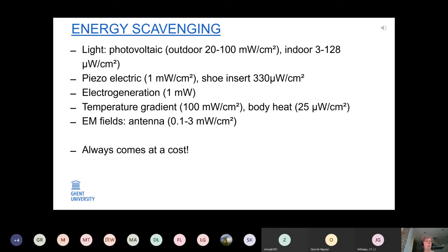But it is important to remember that energy scavenging always comes at a cost. For scavenging light, for instance, you have a dark textile, because it's absorbing the light, that's exactly what it wants to do, which may be inconvenient for textiles. With piezoelectric, you can feel that the resistance of using the textile is a little bit higher. It may be very, very low. A shoe insert, for instance, you won't feel because it will be way below the energy you need for bending the shoe. And an antenna, if you would scavenge all the electromagnetic energy in a room, then none of our mobile phones would still be operational, and also the Wi-Fi signal would be completely absorbed. So this is something we must be aware of.